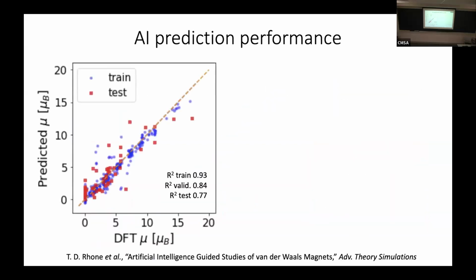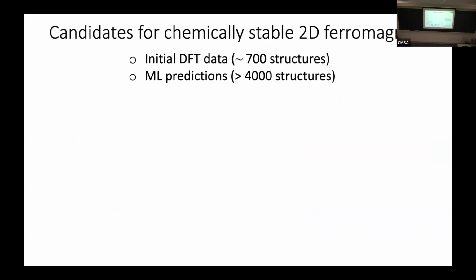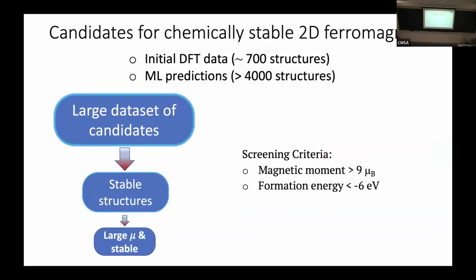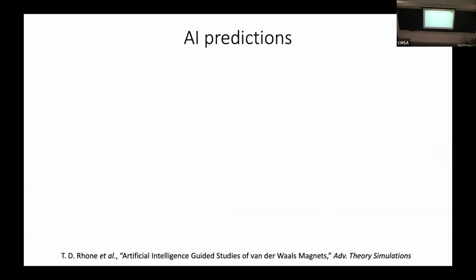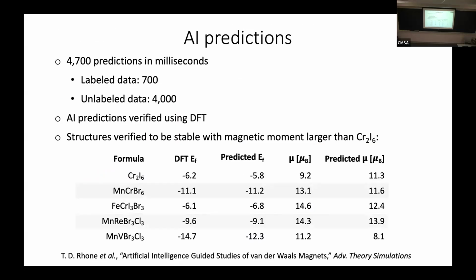So it's like magic. Really, it's fantastic that this works as well as it does. Okay, so what you can do next is collect your DFT calculations and your AI predictions and start doing screening by selecting certain values for your magnetic moment and certain cutoffs for your formation energy, and then going from a large set of candidates to a small set of candidates to find some key materials which might be of interest for further investigation. And that could be comparing the predictions with additional DFT calculations, which we did, and found that our predictions are pretty close to our validated DFT calculations, or first principles validations.